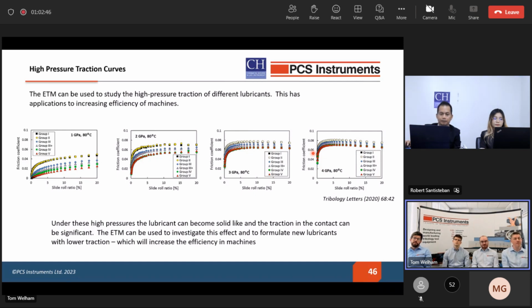So in bearings we are looking at contact pressures around this sort of magnitude. The importance of this region, and understanding how friction is affected by lubricant formulation, is very important. We also see some other interesting things from this graph. We see the leveling off of the traction curve due to shear thinning, and at very high slide roll ratios and very high contact pressures, we also see the reduction of the traction coefficient starting here due to shear heating. It's heating inside the contact.